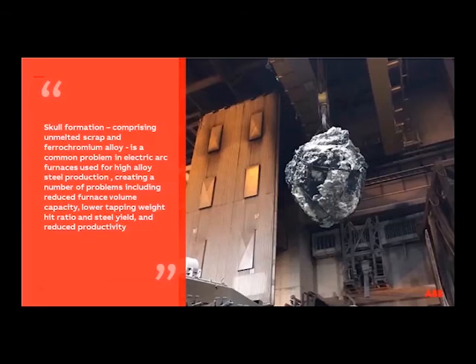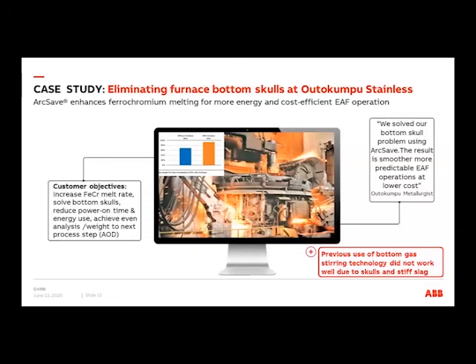One of our next references which had this furnace bottom skull problem was Outokumpu Avesta in Sweden. Here we installed on a 90-ton spout furnace. In this case, they were using 90% scrap, producing 500,000 tons of special stainless per year. The average tap-to-tap time was 65 minutes. For this case, the customer objective was, of course, to increase dissolving of the ferrochromium, which they use a lot in this furnace, and also solve the bottom skull problem they had.